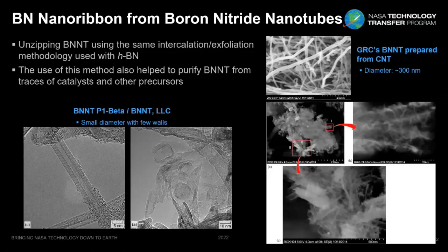As you can see in the second image in the middle, it's the commercial one. You cannot see the tubes anymore. They're just open. And in the one prepared in-house, you can see a little bit of the shape of the tube, but they have a lot of layers opening. You can see how much the surface area of this tube increased. And at the end, these products were cleaner than the original ones. The original ones have a little bit of precursor materials or aluminum, a little bit of catalyst. At the end, they were very clean materials, just hBN or boron nitride nanotubes or ribbons.